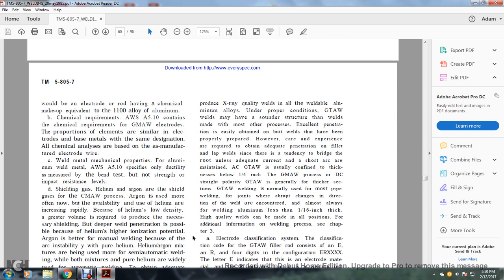Gas tungsten arc welding may have sounder structural quality than welds made with other processes, and excellent penetration is obtained on butt welds that have been properly prepared. However, care and experience are required to obtain adequate penetration on fillet and lap welds, since there is a tendency to bridge the roots unless adequate current with a short arc is maintained. AC gas tungsten arc welding is usually confined to thicknesses below a quarter inch.